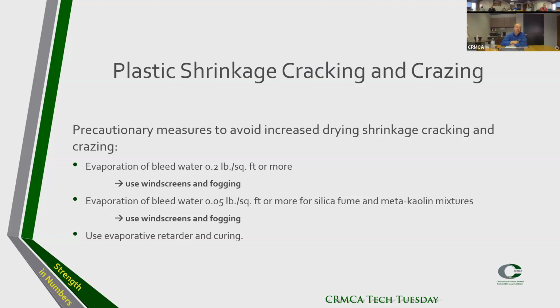One thing that we have seen, and one of the recommendations from our side, is actually with the blended cements, the 1L, some of the 1Ts, to go down to 0.1 or even 0.05 to avoid plastic shrinkage cracking. So the 0.2 is really meant for concrete mixtures with normal type 1-2 cement. Again, for 1L, 1Ts, it is better to go for a 0.1, better a 0.05. It's a little bit more on the contractor side, but that's how we can minimize drying shrinkage cracking and crazing.